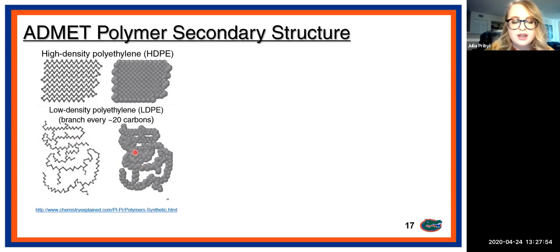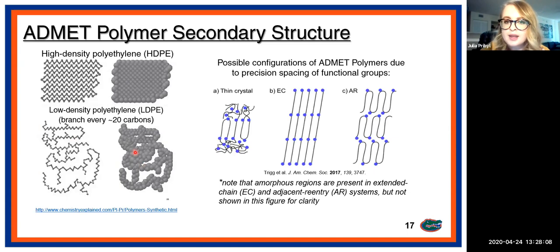And what the ADMET chemistry developed in the Wagner group has allowed us to do is to precisely place any type of branch we want at almost any spacing apart that we want, and study how that impacts the secondary structure. So these figures here on the right are the three different possible configurations of ADMET polymers that are achievable precisely due to the fact that we can control the spacing. The first that's possible is a thin crystal, where if you imagine that the black segments are your polyethylene run lengths, and the blue dots represent the functionality that's incorporated. These thin crystals are basically thin because they are only the thickness of one methylene run length, and then the functional group is actually excluded from the crystal structure.